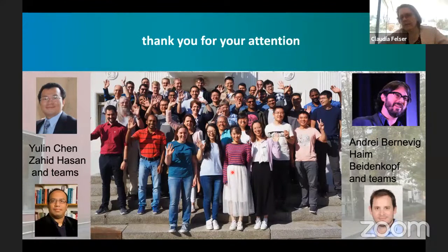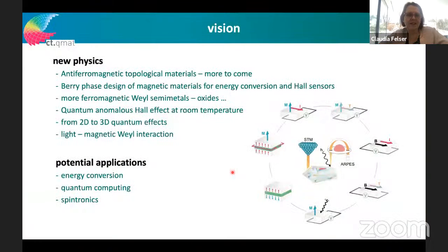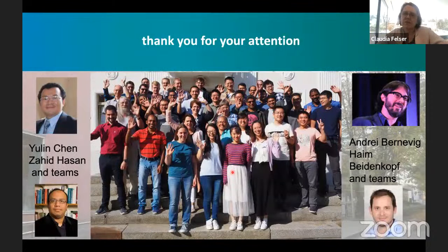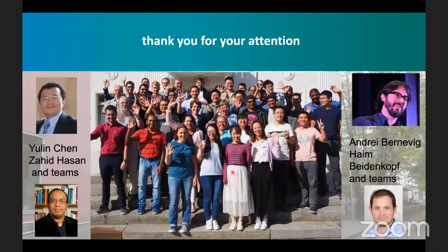I think the magnetic domains I showed for the cobalt 3 tin 2 sulfide 2 are micrometer size domains, so they're micron, so they are not special, I would say, from the domains. So it depends. If you have very nice hard magnetic materials, the domains are larger if you magnetize them once and so on. So this is good for us. But I don't see some special behavior in the domains. Thank you.